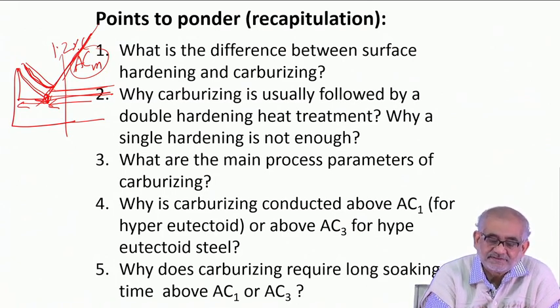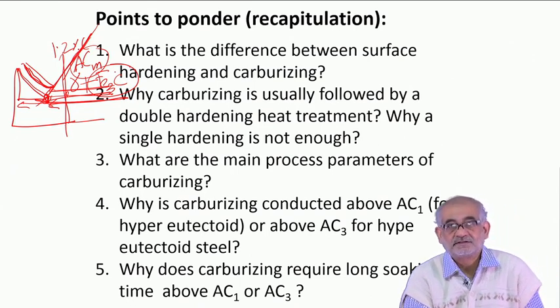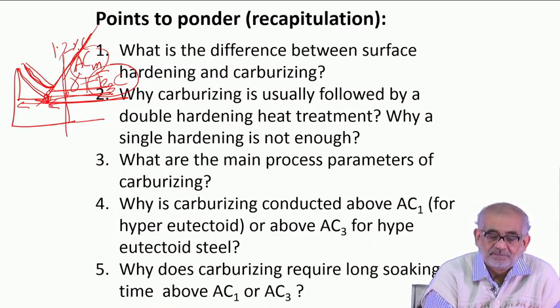But the most important thing is that when you go above the eutectoid temperature for hyper-eutectoid steel, you already have 90% of the volume converted into austenite. If you apply lever rule for 1.2% carbon steel, you can easily see about 80 to 90% of the microstructure is already austenite, and the remaining part will be cementite. Cementite is a hard phase. So even if you retain 10-20% of cementite in the microstructure, it's not going to do harm. Rather, it's going to provide you more hardness, it's going to make the whole microstructure stronger. But your main intention is to convert austenite into martensite.